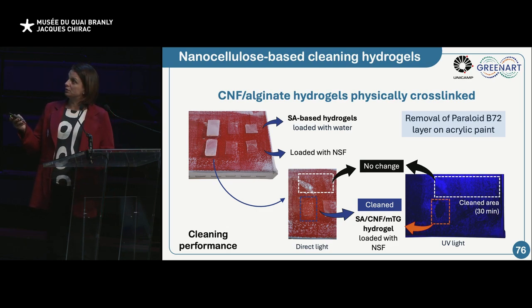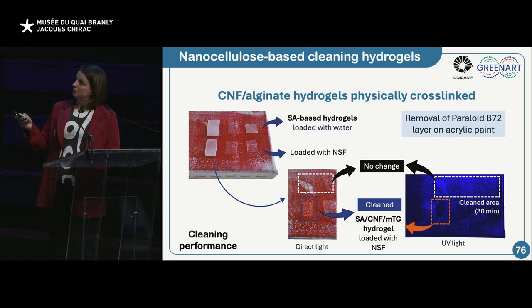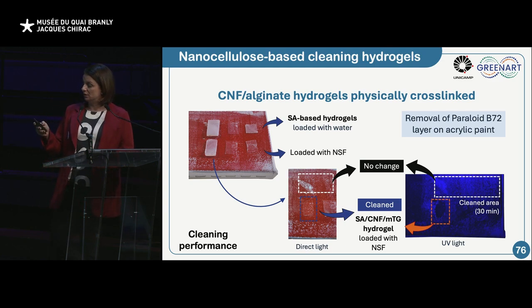This is another example of the alginate hydrogels. Here they are loaded with water. Here they are also loaded with the new nanofluids. And we can see here that this is for Paraloid B72. So we cannot remove the Paraloid with water because it's not removable. But then with this alginate gel here, we have the cleaned area if we use the nanofluid.